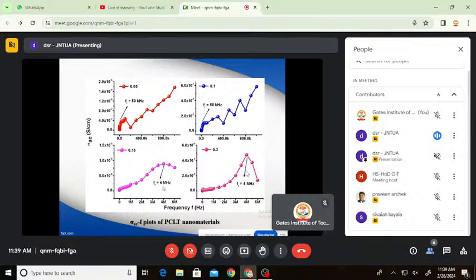Sometimes the trapped charge carriers which exist in dislocation centers, lattice distortions, and interfaces may also be a reason for this. Besides, the y equal to 0.15 and 0.2 contents exhibited an exponential increase in the behavior up to the frequency of 4 megahertz. Above the resonance frequency FR equal to 4 megahertz, gradual decay was noticed for both the compositions.